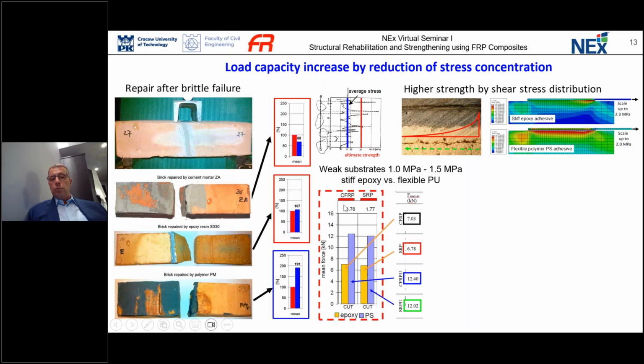So this is the example, 2 cases, CFRP material and SRP material, so carbon and steel fibers as strengthening material, with epoxy resin, this yellow bar, and the blue one is presented with flexible polyurethane. So you can clearly see when we use epoxy resin, the ultimate load, the capacity is up to 7 kilonewtons. If we apply the same system with flexible polyurethane, we received 12 kilonewtons of ultimate load. So you can clearly see both systems, one with steel fibers, another one with carbon fibers.